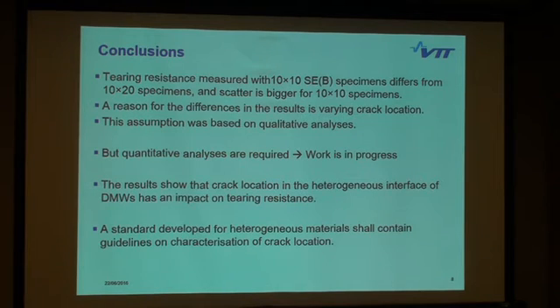And this systematic approach takes us back to the beginning, because dissimilar metal welds are an important part of nuclear power plants. And cracks form in these dissimilar metal welds. During operation, they've been found in several cases. The current fracture mechanical approaches are developed for homogeneous materials. We need systematic, standardized methods to investigate these dissimilar metal welds. The results show that the crack location has an effect on the tearing resistance. Therefore, a standard developed for dissimilar metal welds shall contain guidelines on how to define the crack location.